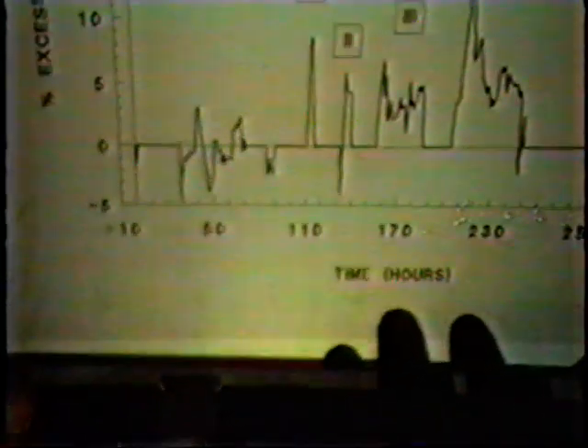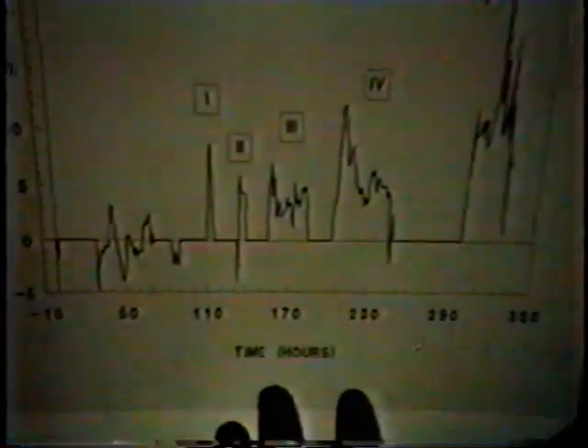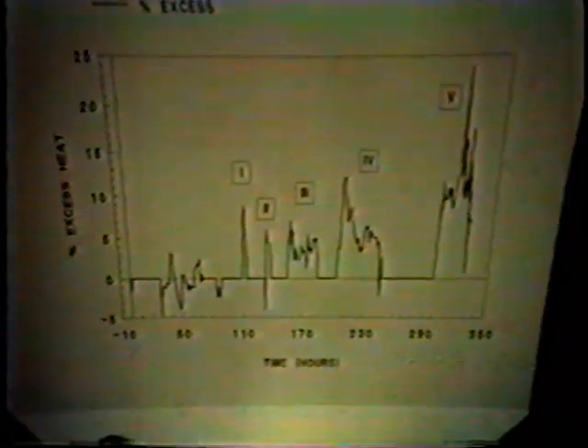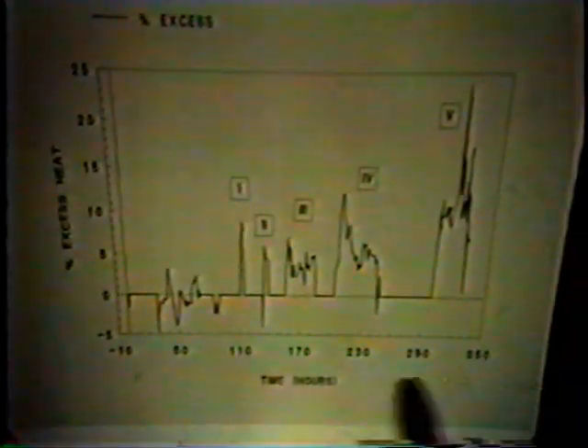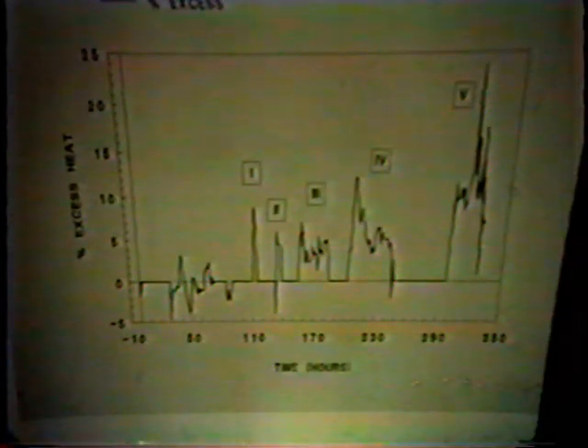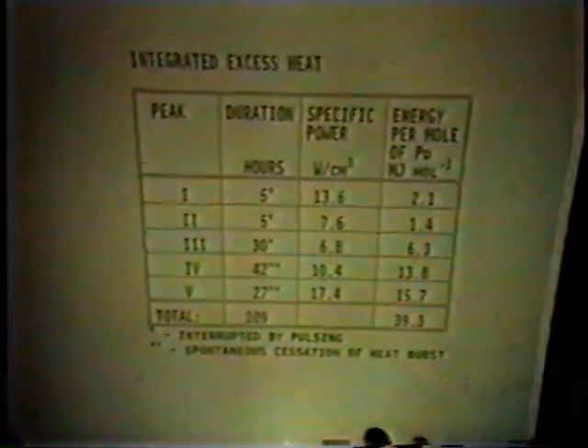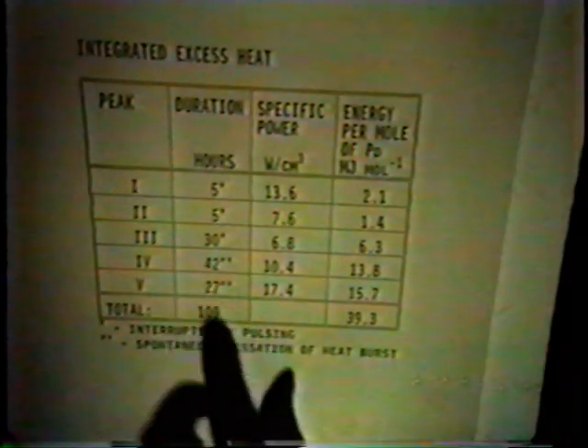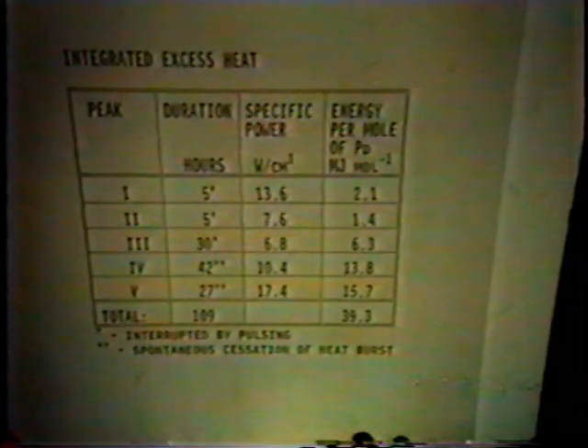And here's the whole lot of the bursts in this particular electrode where the pulsing caused the D to sweep up. And there are very interesting things. We could talk about these bursts for perhaps 10 minutes because there's a lot of structure in them. And you can see there's a rough tendency, over a rather large time, about 300 hours, 2 weeks, something like that, to go up. The pulses increase: small pulse, bigger pulse, small again, bigger, bigger, bigger, as time went on. And the next table shows you to what extent we interrupted them, and to what extent they ran out of steam, as it were. The first 3 were interrupted by more pulsing, and the last 2 just stopped. They stopped after a rather long time, 42, 27 hours.